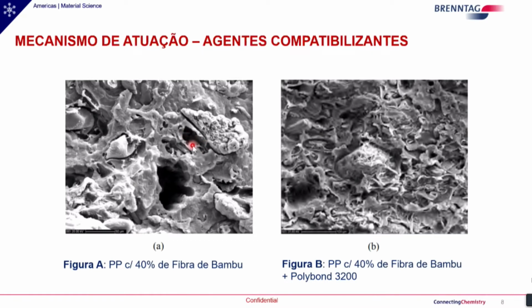Well, what is the impact of that? Precisely these gaps, these voids you see here in the image. And they happen, these voids happen, because the fiber is removed. This microscopic analysis was conducted after a traction assay in a polypropylene with bamboo fiber. And that was the impact without using the compatibilizing agent.